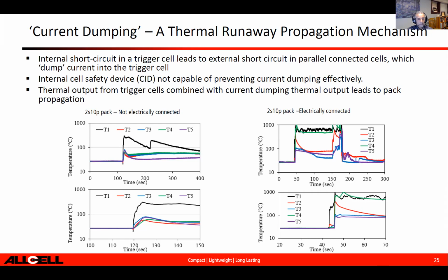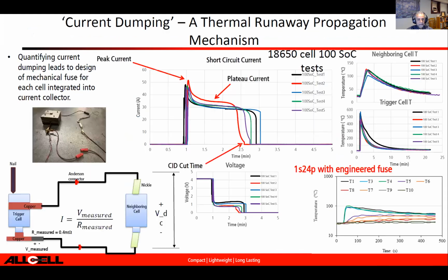And that prompted us to do further investigation to understand if the internal cell device, which is called the CID, is capable or not capable of preventing that current dumping. And what we've done, we actually done extensive studies on those CIDs. We took cells and we started short-circuiting them and measuring the current that comes out of them. And what we found continuously, especially at 100% state of charge, that those cells dump significant current. You're talking about a peak of 50 amps or more and a constant current of more than 30 amps for a few minutes, which is enough to drain that cell completely.